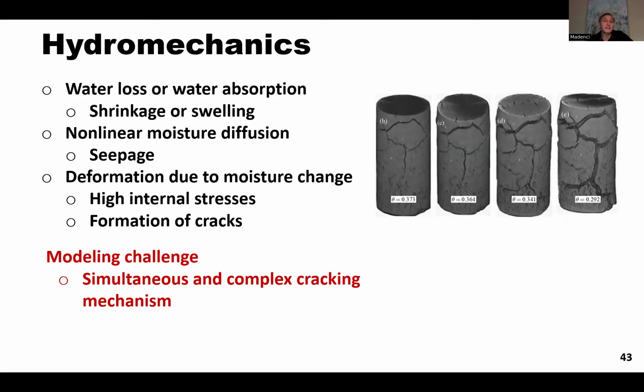I picked this problem because the equations are complicated. This material that you have here could be a rock, for example. It could absorb moisture, so you could have shrinkage or swelling, depending on whether you're drying or absorbing. Moisture can seep through, you can have deformation due to moisture change, you can have internal stresses, and as a result, you can have formation of cracks. So the modeling challenge here is, of course, the coupled field equations, but also crack initiation and crack growth in an unguided fashion.